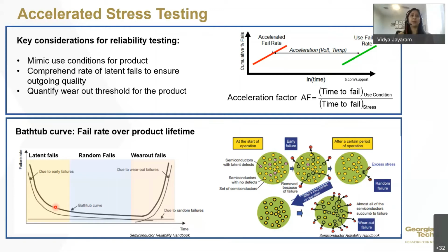This could be mostly induced by your process level yield loss. For example, in the beginning, when we spoke about voiding in the solder joint caused by process-induced failure, maybe the reflow conditions were not optimized for the void to escape effectively. These voids in the package can grow and lead to an open and early failure, but that's induced because of the processing. So this is something that's needed for every single electronics package, where you want to weed out all the early failures and the latent fails, so that you can focus on what you would expect to be a normal distribution for your process conditions and your fail rate.